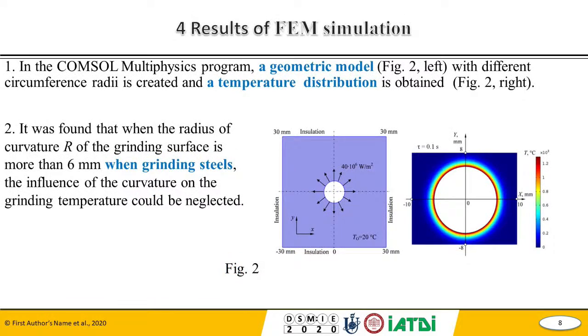Slide 8 shows the result of FEM simulation. First, in the COMSOL Multiphysics program, a geometric model, see figure 2 left, with different circumference radii is created and a temperature distribution is obtained, figure 2 right. Second, it was found that when the radius of curvature of the grinding surface is more than 6 millimeters, when grinding steel, the influence of the curvature on the grinding temperature can be neglected. The next slide, please, number 9.